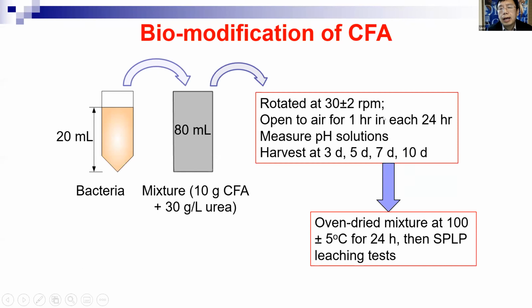So we rotate that, and then we give air, because the bacteria still need air. So we measure the pH, and we harvest at several different days. Then we also oven dry the mixture, and we use the SPLP to do the leaching testing for this one, for fly ash.